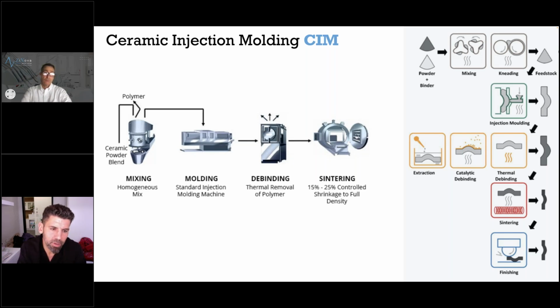And then you have these prefabricated molds. In our case, they're shaped into dental implants. Then the binder is removed, and then it is sintered. And at the end of this process, you obtain your final shape.